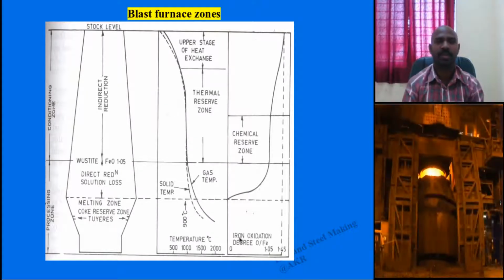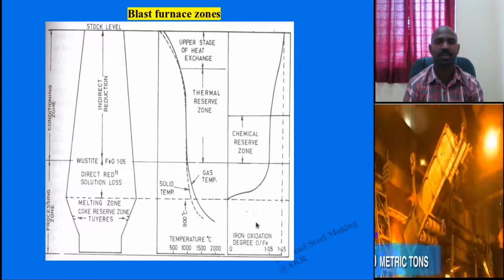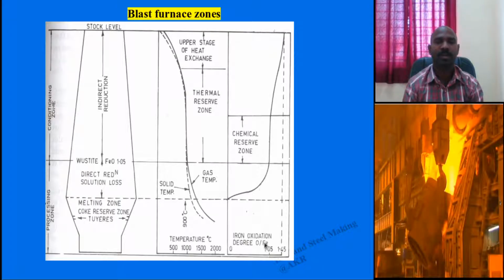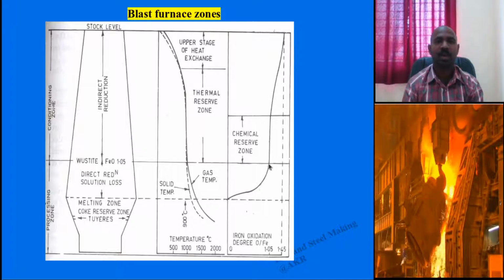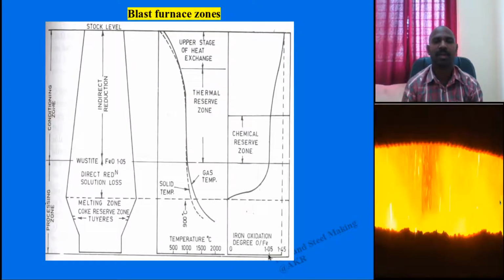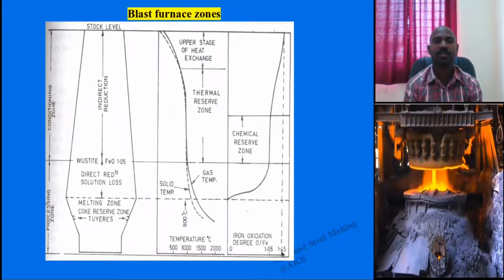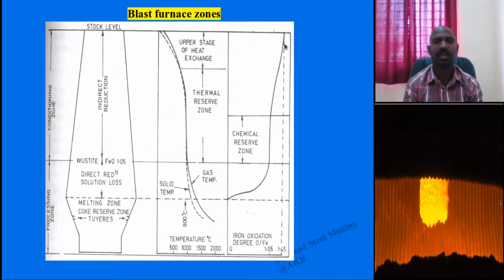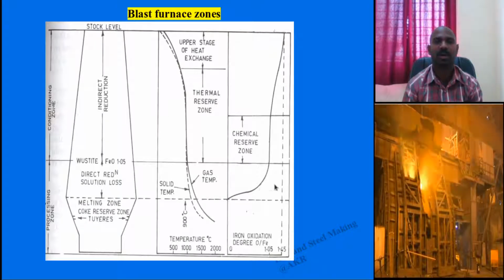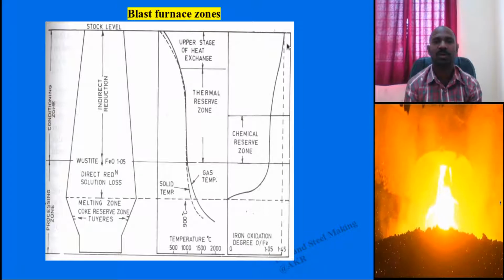And in the case of iron oxidation, how much iron is getting oxidized, how much iron is going into the slag, how do you calculate the oxygen and iron ratio? These graphs will give you the detail. Near the Bosh zone it is around 1.05, and when you see at the stack zone, extrapolating into the hearth, it is 1.45 oxygen to iron ratio.